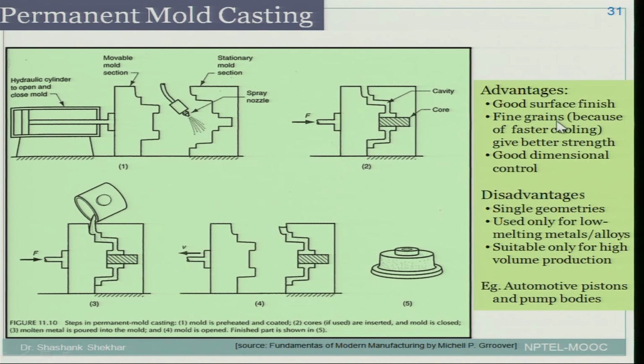You get fine grains because the heat conductivity is very high, so you get a very fast cooling rate giving very good strength, and you can also get very good dimensional control. The disadvantage is that you can only have a single geometry. This particular die cannot be used for any other purpose; you cannot make any other shape. So this is used only for low melting metal alloys.